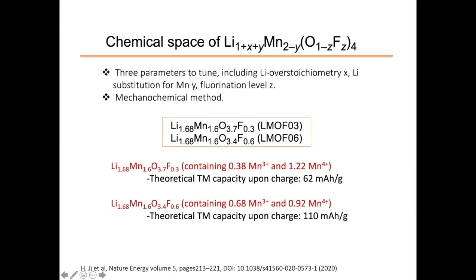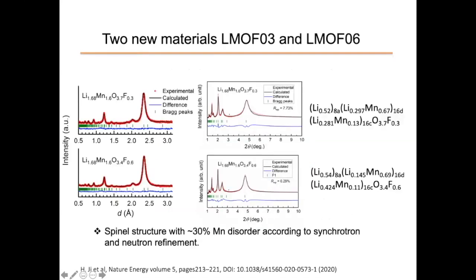So here are two compounds we made and published on recently. As you can see, this is four anions. It's 0.3 fluorine. But if you add up the lithium and the manganese, it is almost 3.3. So we have about 10% cation excess over the spinel, and it is also heavily lithium excess. The material that I'll refer to as FO3 is the fluorinated O3, and the material I refer to as FO6 is just the fluorinated O6.